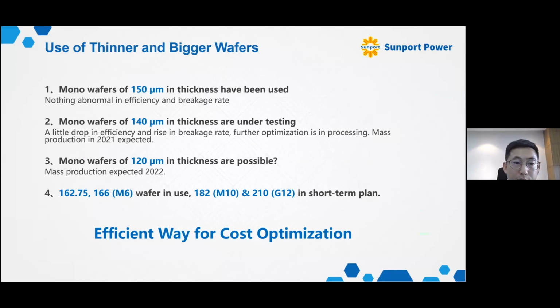As we all know, the use of thinner and larger wafers is becoming the trend. In this respect, the stress-free back contact design allows us to use thinner wafers. At the moment, 150 micrometer wafers have been used in our mass production, and we are exploring thickness down to 140 and even 120 micrometers within these 2 years. From the other side, we are promoting the use of larger silicon wafers up to M10, which is 182, and G12, which is 210 millimeters, in a very short-term plan.